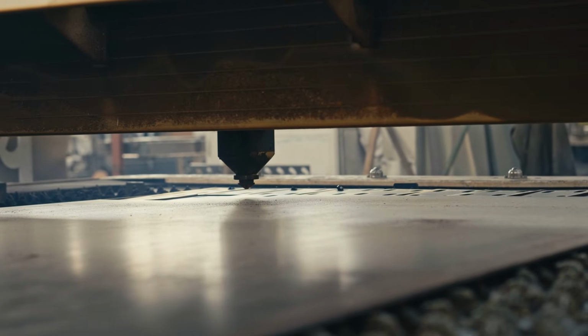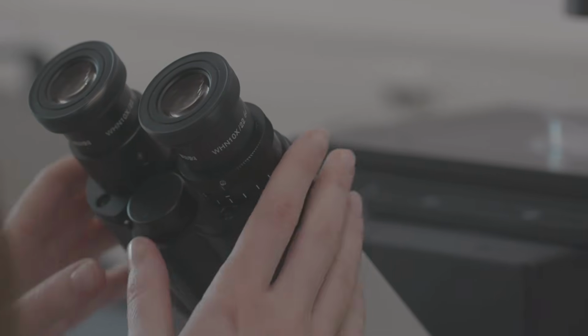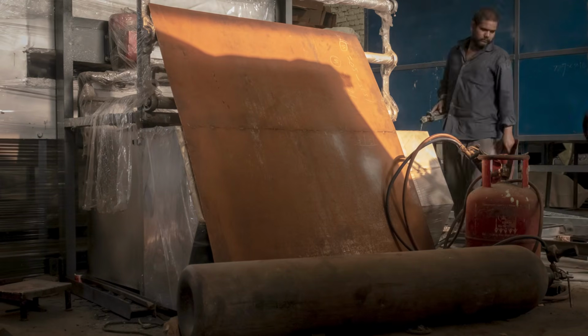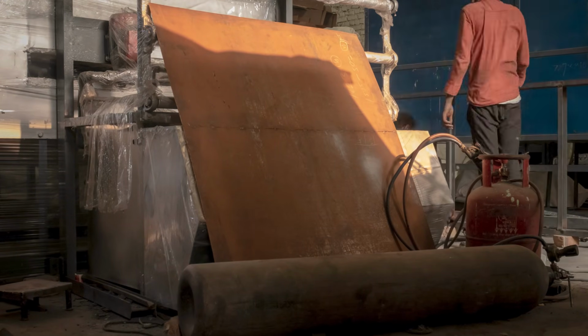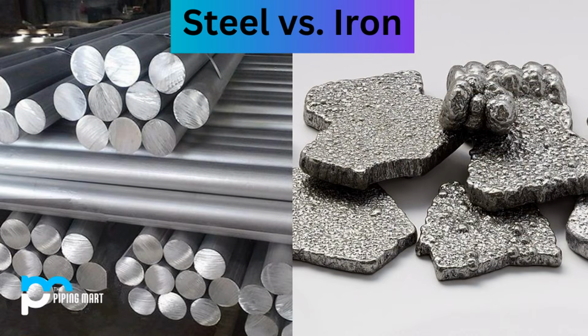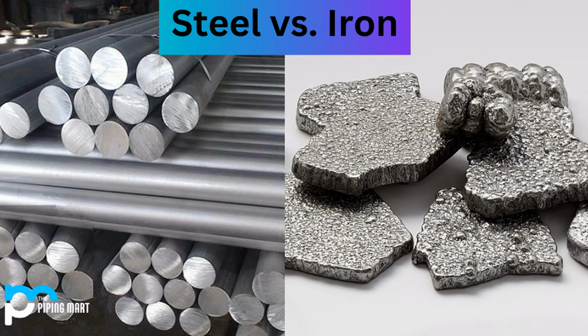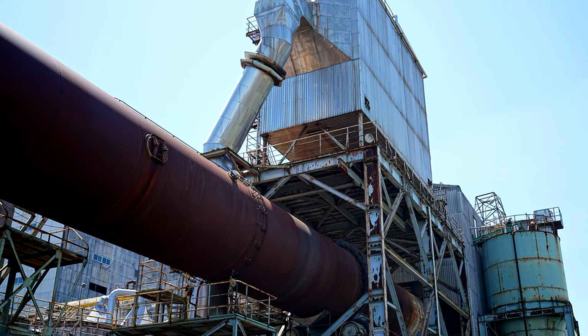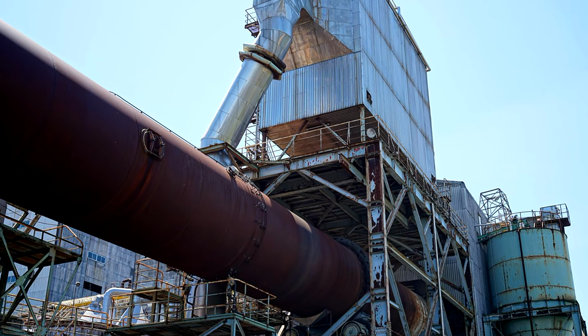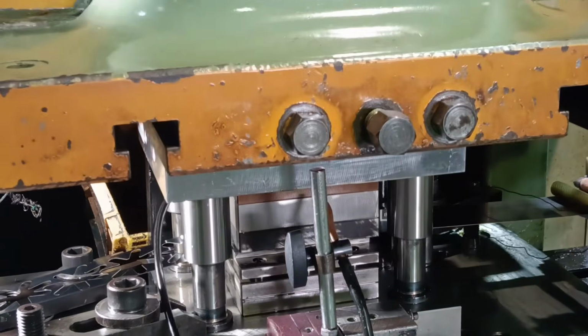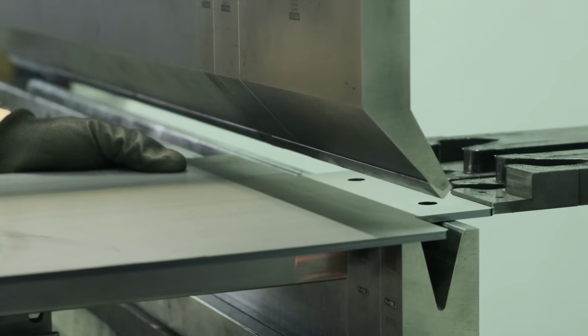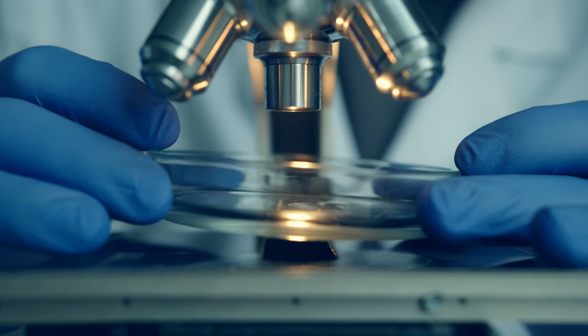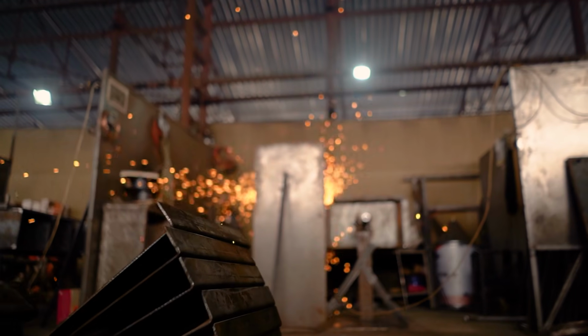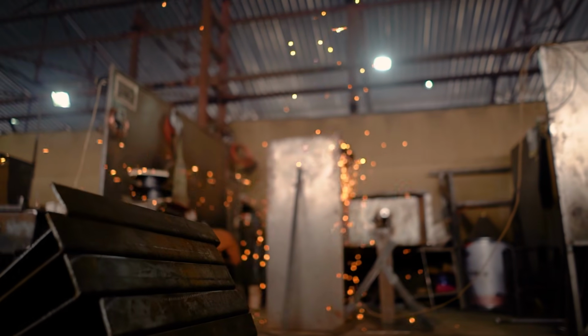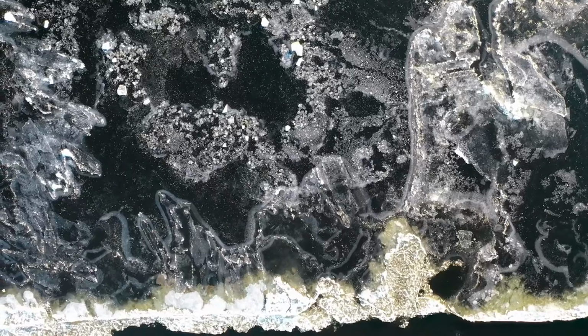The second thing was the steel itself, and this is where a metallurgist in Cambridge changed the industry. The plate being produced for wartime hulls had a chemistry that nobody at the time recognized as dangerous. Sulfur content too high. Manganese too low. Steel like that has a property called a ductile to brittle transition temperature. Above it, the metal behaves the way you expect metal to behave. Put too much load on it, and it stretches, yields, deforms, tears slowly, and gives you visible warning that something is wrong. Below it, the same steel stops tearing and starts shattering. It behaves less like metal and more like glass.